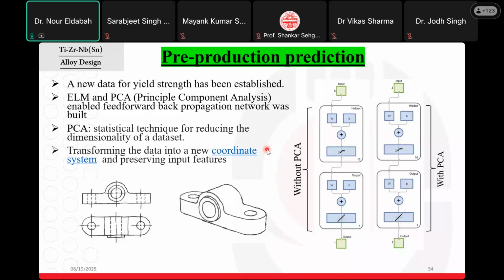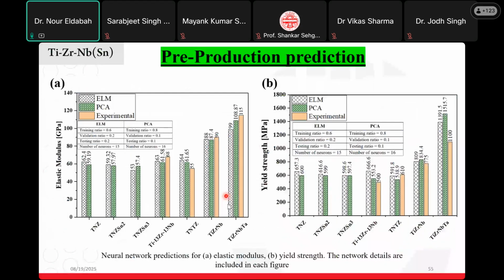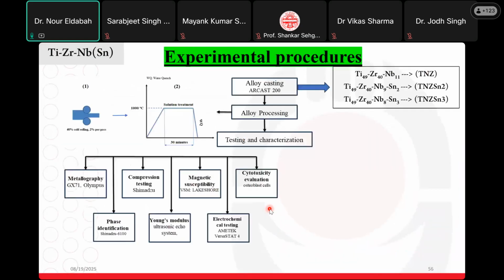After we successfully trained both the extreme learning machine and the PCA network for the yield strength and elastic modulus prediction, we ran our prediction for our proposed compositions that will stabilize the BCC phase, and compared the prediction of the two neural networks with the experimental results for the compositions that exist in literature. We can find that the neural networks for both elastic modulus and yield strength behave well in our case. We just need to characterize our alloy and stabilize the BCC beta phase at 1000 degrees Celsius.